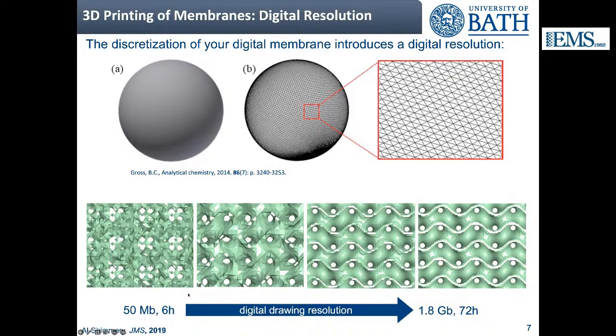However, this has an effect. You can imagine that you always want the highest possible digital resolution, but this also has a practical effect. This image on the left is 50 megabytes, and it takes about 6 hours to print. This would be a number of 47 millimeter disc membranes. If you go to the image on the right, this file has now grown to 1.8 gigabytes, and it takes about 72 hours to print. So the higher the digital resolution, the more memory, so the more powerful computer you need, the more powerful 3D printer you need, and it takes more time to print.